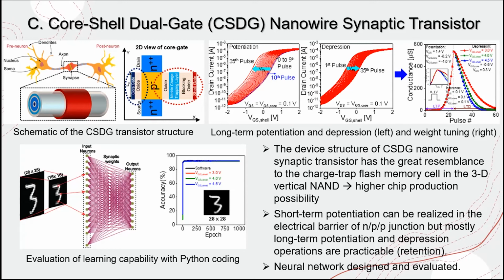In the reversed manner, you can deposit the dielectric materials like gate oxide, the ONO storage layer, tungsten, channel material and oxide core. In the reverse manner, the materials can be stuffed into the narrowly drilled hole in the vertical array. The only difference is the material combination. If you replace the oxide core by a metal gate or highly doped polysilicon gate, we can call it a core gate. There is another gate at the shell, so we can call it core-shell dual gate. They can be operated independently.